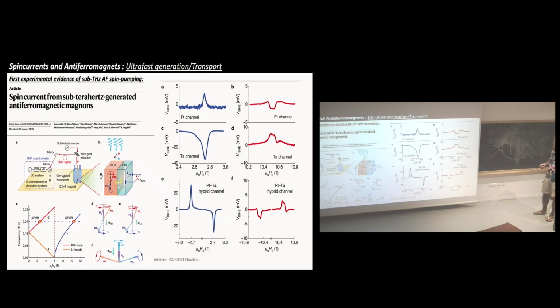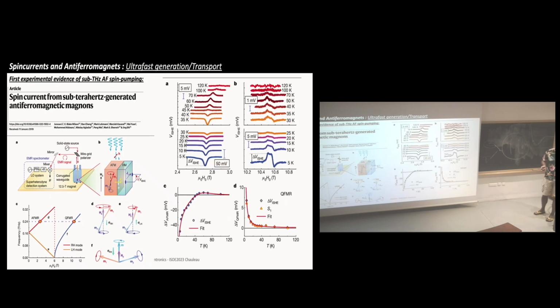But as life is never so easy, it's a bit more complicated than what they thought. So it's not a direct proof of it, because they realize that actually the quasi-ferromagnetic mode and the antiferromagnetic mode have opposite sign. So meaning actually what you are doing first is that because of heat, you start populating the lower branch. Since it's at lower energy, it's easier to populate with thermal magnons. So basically you compete between two things. You compete between incoherent thermal magnons.